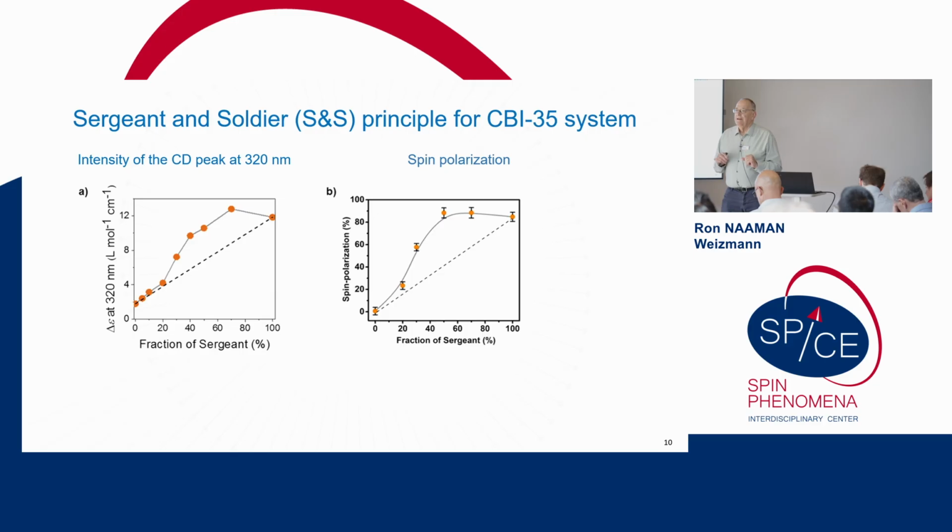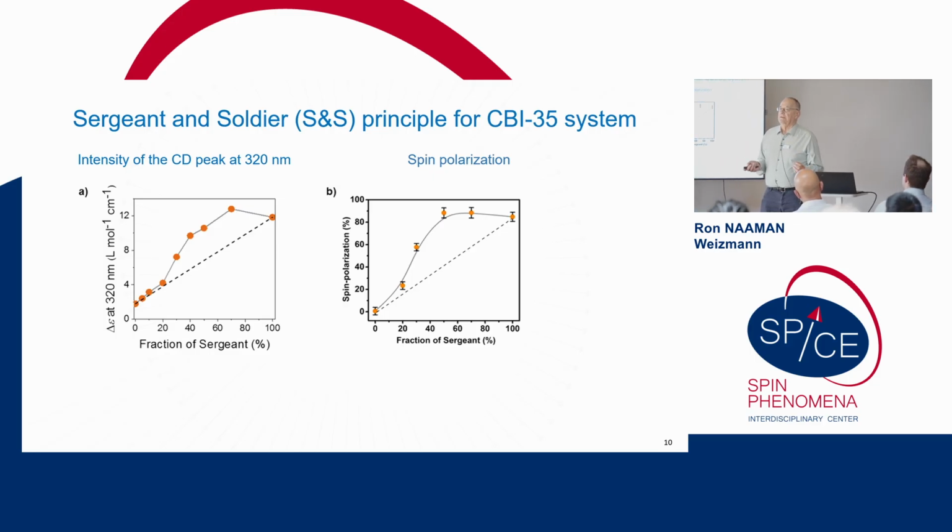But it's related to the anisotropic polarizability. So it tells us that the CISS effect depends on the same anisotropic polarizability that optical activity depends on. And that was verified by many groups since then. And it tells immediately that if we want to understand the chiral effect, we must include polarizability. And the polarizability is not a property of a point, it's a property of the whole structure.